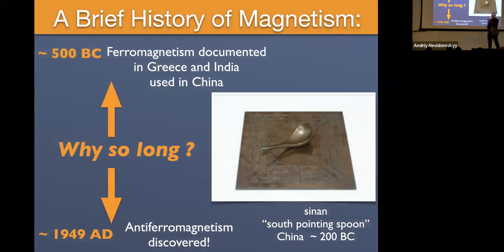And those two states, ferromagnetism and antiferromagnetism, as I mentioned, if you pick up Ashcroft and Mermin or any of the standard solid-state physics books, they're almost described in the same breath, right? It's really the same phenomenology that applies to both of them, but they have vastly different histories, actually. The reason is that a ferromagnetic material will generate magnetic field lines that build up and add up coherently and will give you a substantial magnetic field outside the material itself, and that will allow you to stick fridge magnets to fridges, for example. And also, you can make little needles out of ferromagnetic materials, and they'll align with the Earth's magnetic field.